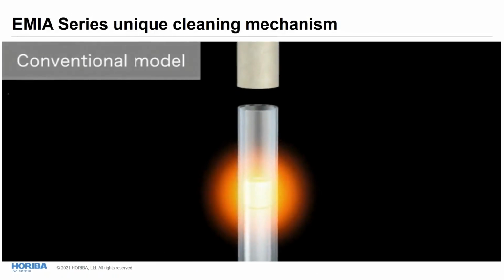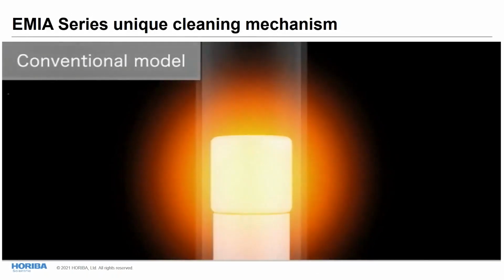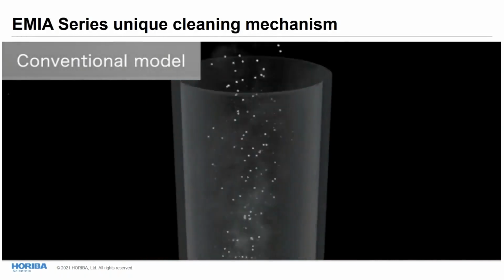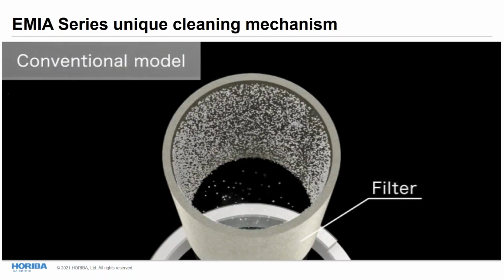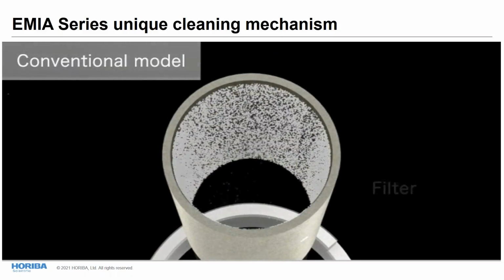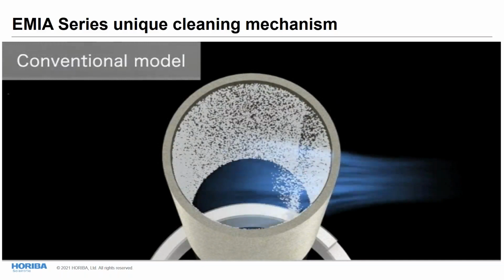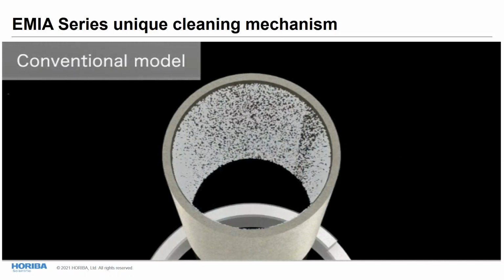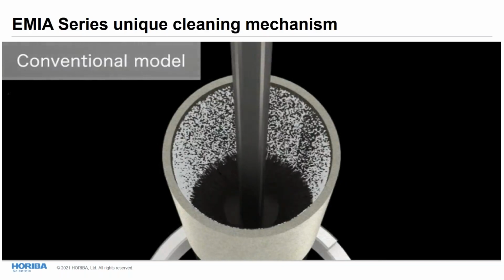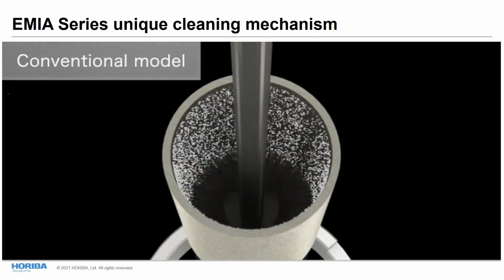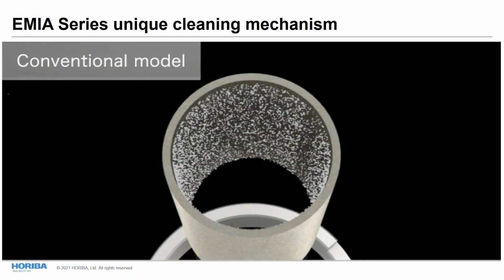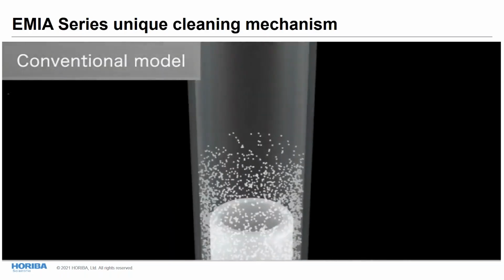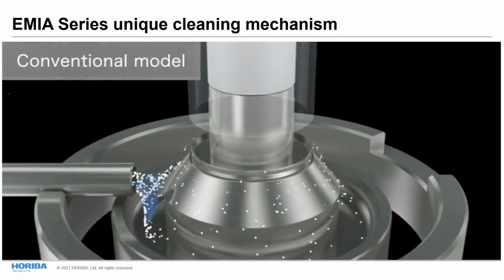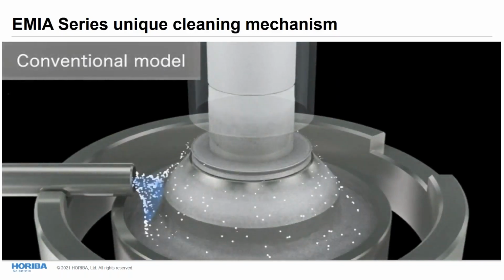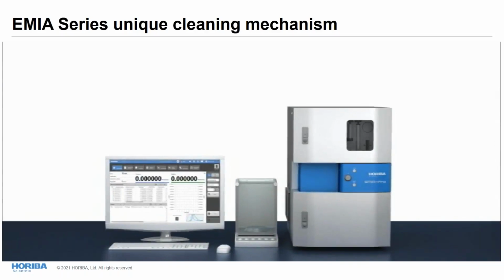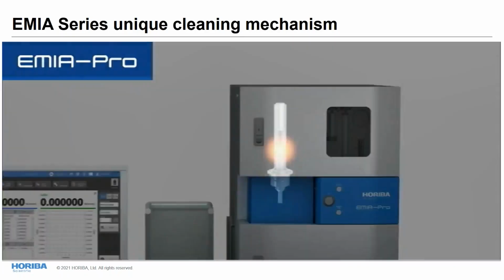Let's look a little bit in detail at this cleaning system. You look at a conventional model. It will use a brush that will require slower mechanical movement. The dust generated during combustion is accumulating on the inside of the filter. The gas goes through to be analyzed by the detectors, and then after the analysis, the brush will mechanically remove the dust that will fall down into the crucible and around the crucible, where it will be collected by a vacuum cleaner. There is a lot of dust with this setup that will accumulate on the side, as you saw in the picture before, and that will require this frequent maintenance.